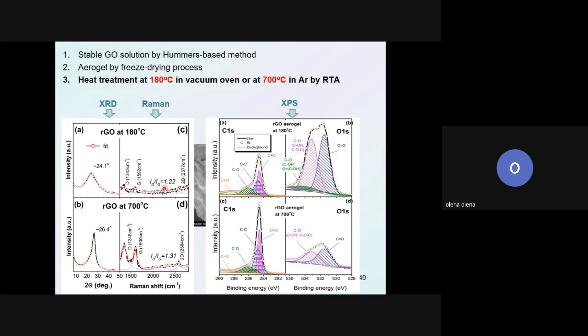We also make a Raman study. And as you can see, the intensity ratio between the D and G peaks increases with temperature. It means that the defects are increasing. XPS for this reduced graphene oxide aerogel shows us that, of course, the main difference is with the oxygen: oxygen groups almost disappear with increasing temperature. You see the intensity for 180 and for 700. So it means that the reduced graphene oxide aerogel annealed at 180 still has some oxygen functional groups after annealing, in comparison with the aerogel at 700, where we almost didn't observe them.